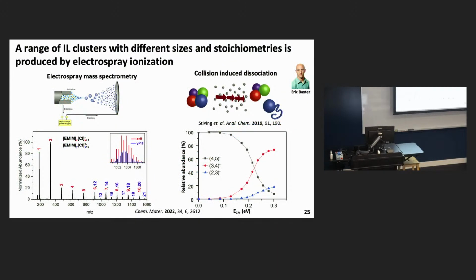So where we started was in the gas phase. You can take a mixture of ionic liquids in methanol and you can electrospray them to get a distribution of ions. When you do that, in anion mode, you see something that looks like this, where you have a distribution of clusters containing different numbers of the imidazolium cations and chloride anions that make up these ionic liquids. You also see doubly charged species that are mass degenerate with the singly charged species. So it's extremely important to have the mass resolution to be able to distinguish the two and know that you have a pure species when you do the deposition.